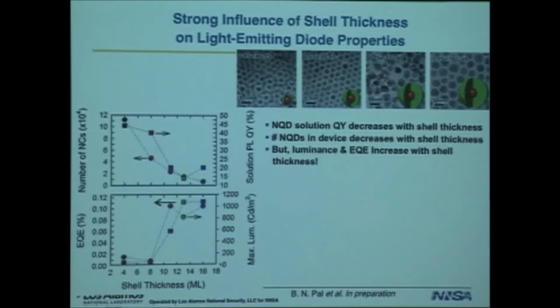In addition, because our giant dots are big compared to the thinner shell counterparts, if you create a monolayer of either material, you effectively have fewer emitters in the giant dot monolayer compared to the thin shell monolayer. So in the case of a solid state monolayer, we have fewer emitters, and in the solution phase, they were poorer emitters. But what do we find as we increase shell thickness? Instead, we find that our EQEs go up significantly, as well as our maximum brightness. So our solution phase properties do not correspond very well to our solid state properties. And so why is this happening?